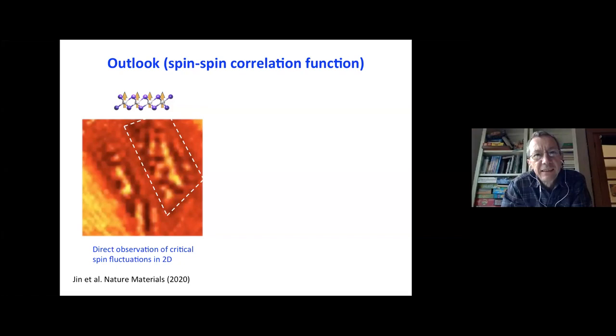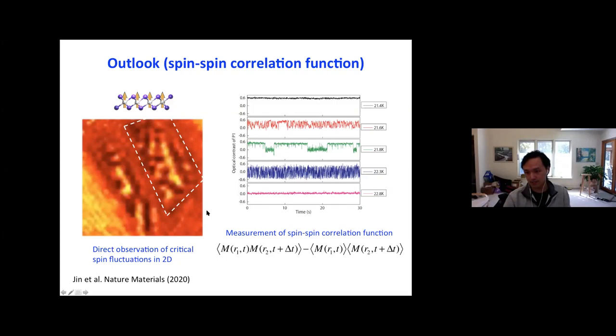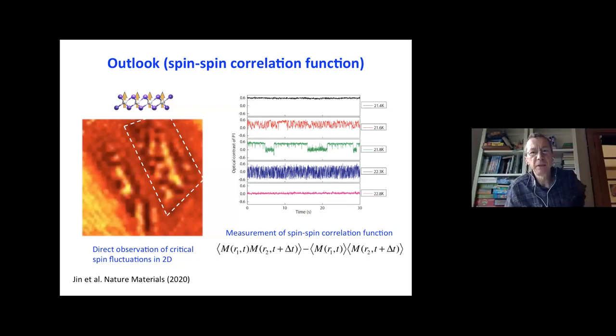As I mentioned, you can calculate the time correlation function as well as the spatial correlation function using these images. But at this point, what's limiting the spatial correlation function is actually the sample inhomogeneity. Different parts of the sample have slightly different TC, so we don't really see a divergence of the correlation length through the entire sample in this measurement. But it's something like a spin noise measurement, right? Yes, it's like a spin noise measurement. Okay. Thanks.